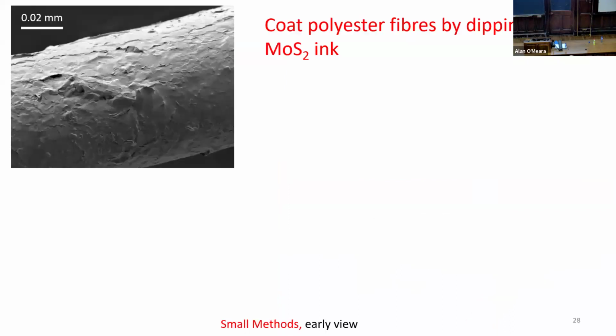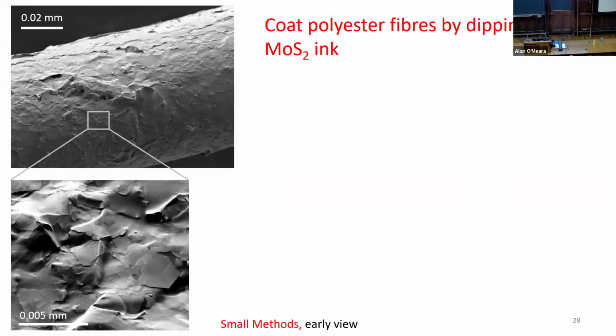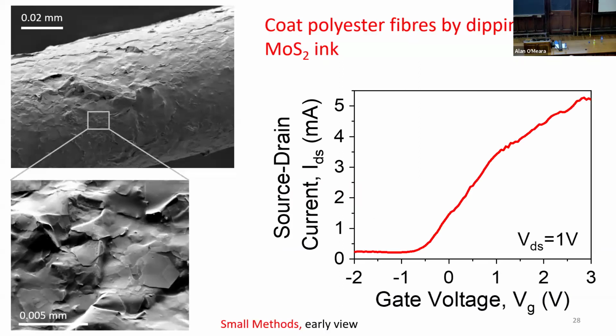So this is a piece of polyester fiber coated with 2D materials just by dipping into an ink. Looking up close, you can see these are the 2D materials sitting on the surface. And this is a transistor response, and it's actually quite good. So around now, the record for performance in a printed transistor, as determined by the mobility, which the physicists will know what that means, is around 10 centimeters squared per volt second. These ones go up to about 15, 20. So these are beyond state-of-the-art printed transistors, and they're printed on the very fibers of the clothing. So I think that's pretty cool.